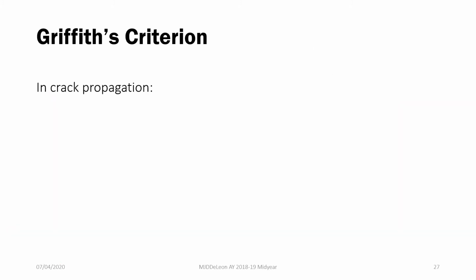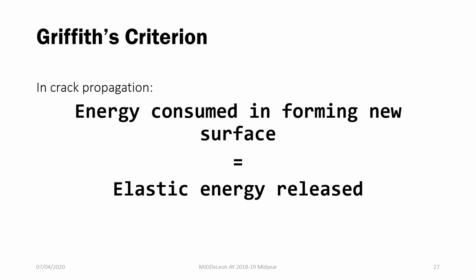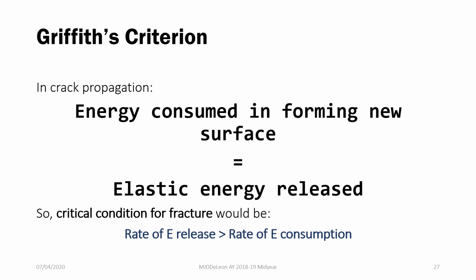So, thinking about how your crack would propagate, makita natin learning about stress concentration, the stress that is shouldered by the crack tip, that for a crack to propagate, yung stress at the crack tip must be greater than the theoretical strength of your material, sorry. So, ginawa to ni Griffith as a criterion. In-state niya lang in another way. In crack propagation, the energy consumed in forming a new surface is equal to the elastic energy released. So, for a crack to propagate, for fracture to happen, the rate of energy release should be greater than the rate of energy consumption.